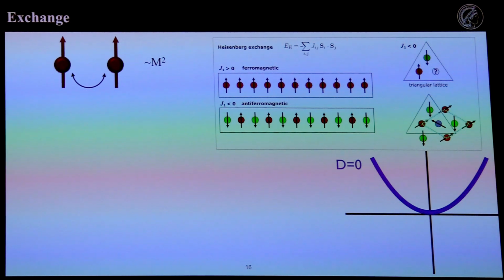And this is one of the first cases of non-collinear, and if you've seen the work of Jakub Železný and others, this has very interesting Berry curvature responses in manganese 3 tin, manganese 3 iridium, in cases like this. As you look at the magnon dispersion of this, it's just a q-squared dispersion, so a quadratic equation that Frank likes a lot.